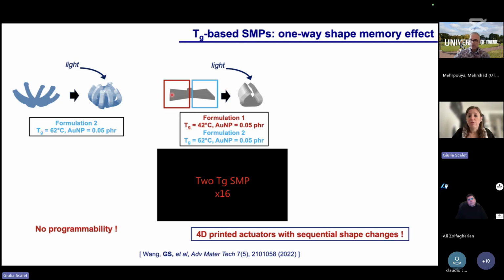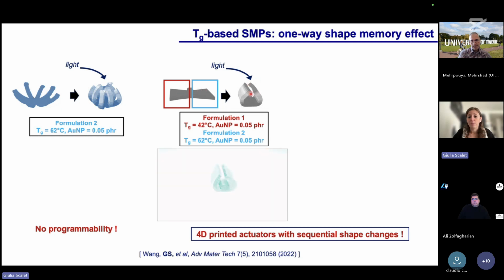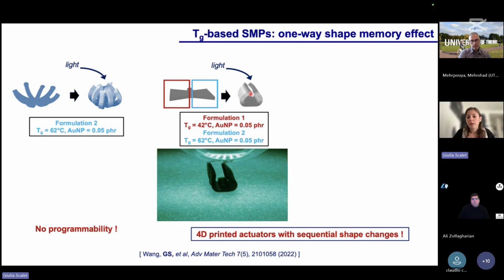So a structure made of two polymers with different chemical composition, and this different chemical composition led to different glass transition temperature with the same amount of gold nanoparticles. In this case, this is the initial shape. This is the deformed temporary shape. Upon light irradiation, you can achieve a sequential shape change. So it is possible, again, using just one-way shape memory polymers, but with multiple polymers within the same structure.